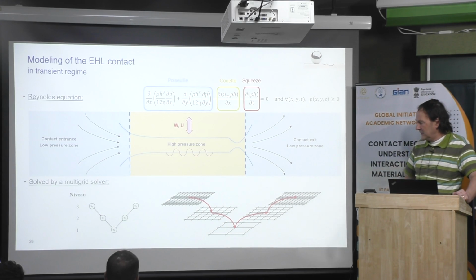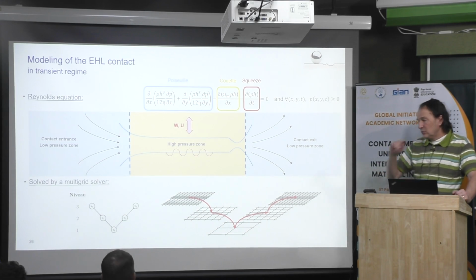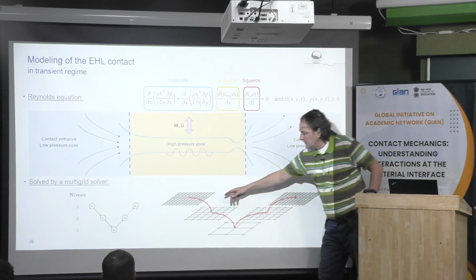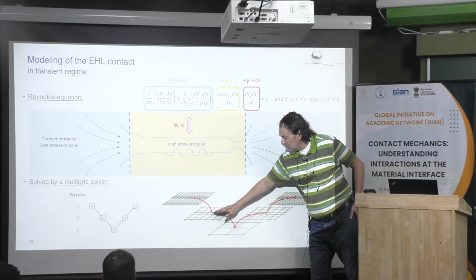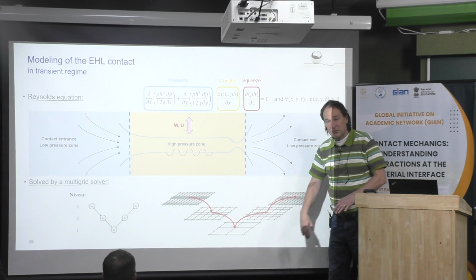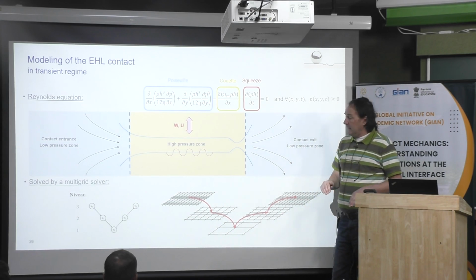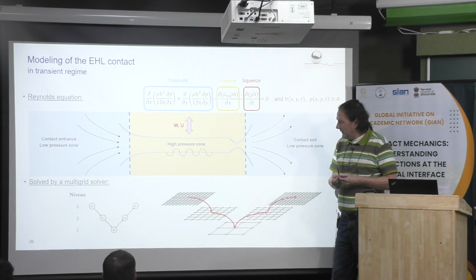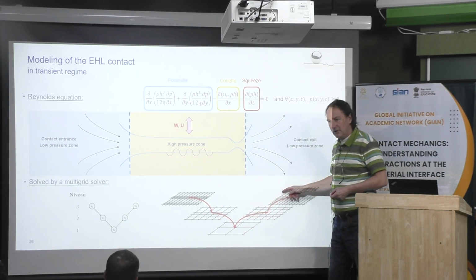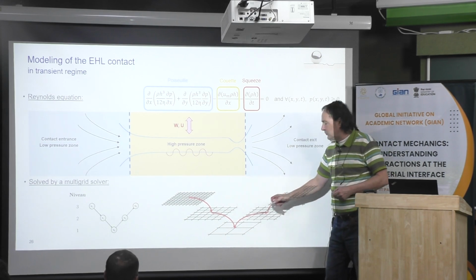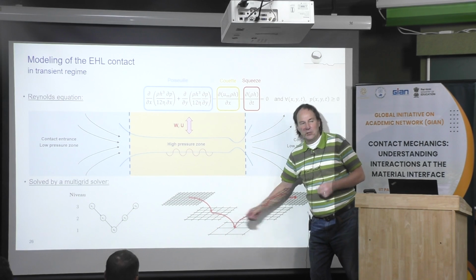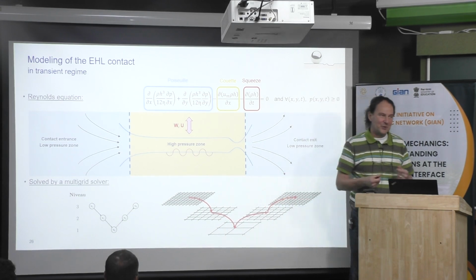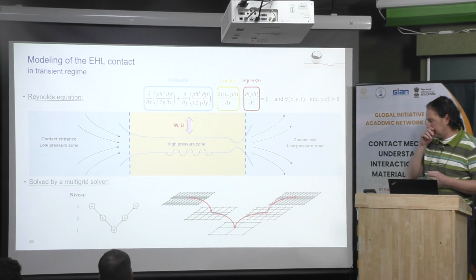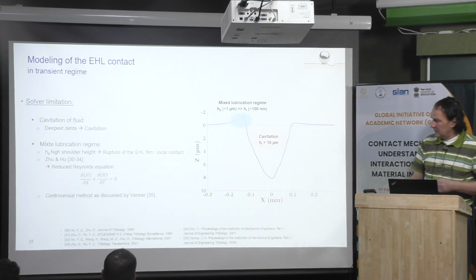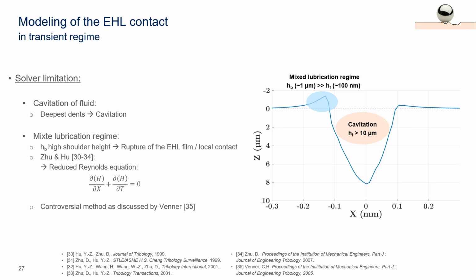Okay, this is what we did, and as I said, we don't use that for solid mechanics because it's quite complicated. You have to jump between one fine mesh to a medium mesh to another mesh, and you have several levels. You can have up to 7 or 8 levels, but there is some recipe because sometimes you have to do some V cycles or some W cycles. You have to remain several iterations at a level. Okay, there is some recipe, some experience to deal with that. But okay, for that we use this method, and then we were able to do some simulation, some EHL simulation.